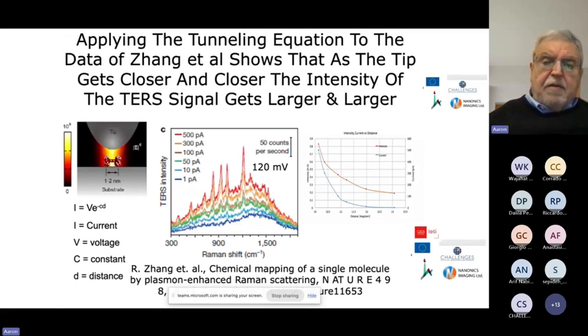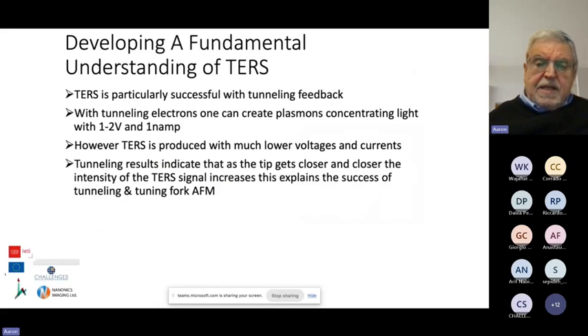And when you increase the current, okay, you can see based upon the equation, the distance becomes smaller and smaller. And therefore, as the distance becomes smaller, the tip comes closer and closer, and therefore an effect occurs on the material that increases the Terz effect. The same tip, the same sample, just the distance. That's why tunneling, and that's why even AFM with a tuning fork works much better. So tunneling results that indicate that as a tip gets closer and closer, the intensity of the signal increases. This explains the success of tunneling and tuning fork AFM.